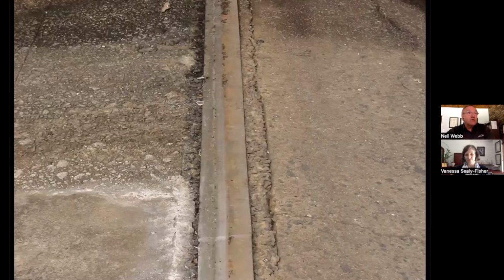This photograph actually is of a spillway in a dam, where the steel strip in the middle is a stainless steel bed where the seal of the dam gate sits. And when the gate is open, the water rushes through there, and you can see the way it has both worn and dissolved away a certain amount of the concrete paste that acts as the glue, if you can call it that, the cement, excuse the pun, between the actual aggregate pieces.